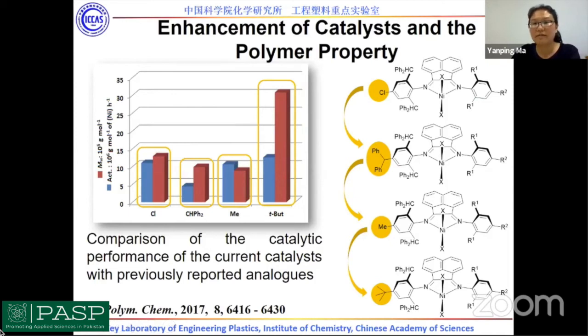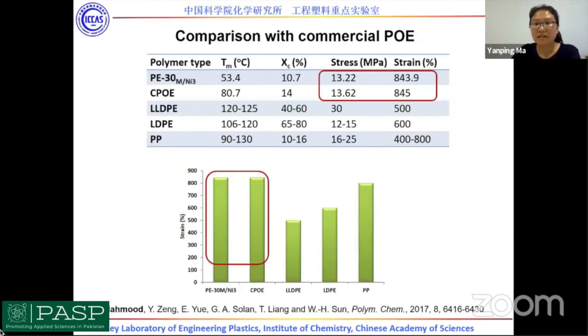Since the branched polyethylene in our group also has elastic properties, how about it? We compared the mechanical properties of the produced highly branched polyethylene with the commercial polyolefin elastomers. We found the mechanical properties are almost equal.